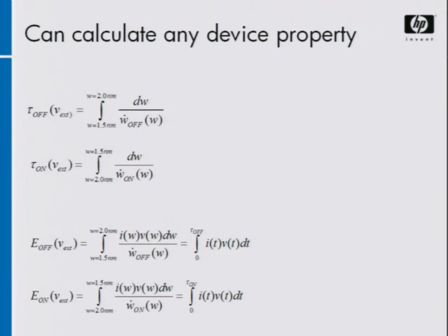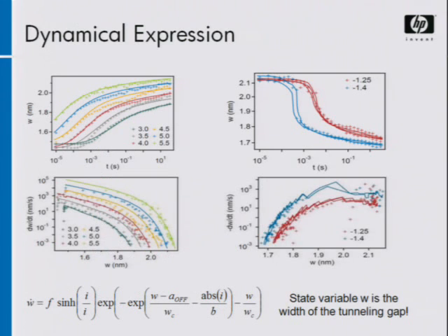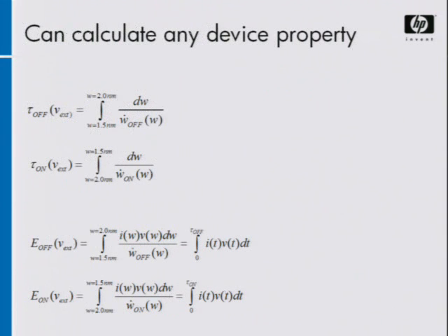One interesting result is that these data essentially predict that the state lifetime is infinite. In other words, over 7 orders of magnitude, we don't have enough data to predict how long the state lifetime is. So it looks like it diverges literally. So what that's saying is that the diffusion velocity of these things is really very, very small.